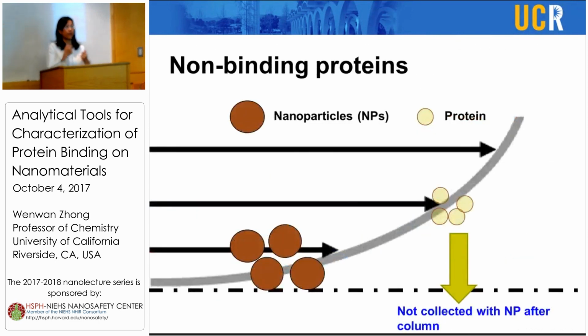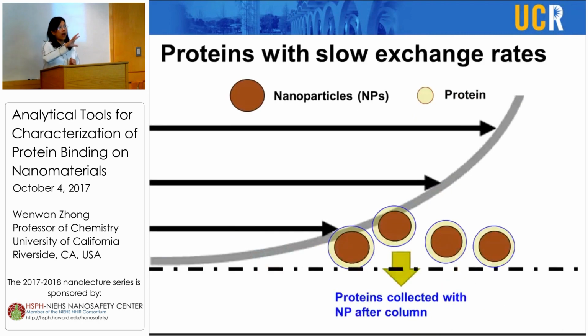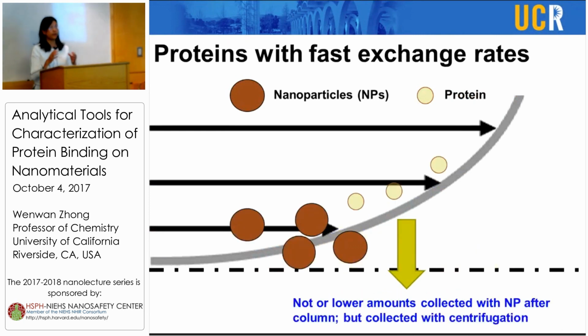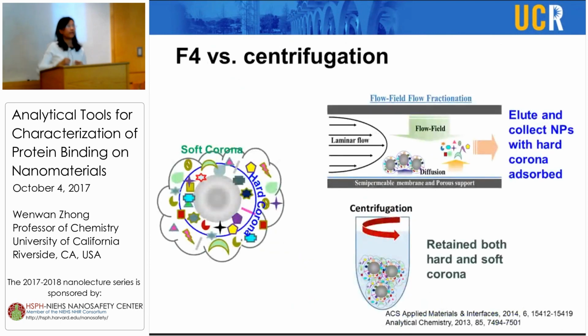So when we have a protein that is non-adsorbed onto the particle, because this particle size is quite different from a regular protein, with molecular weight around 100 to 150 kDa, the particles are much larger, right? So we can separate the particle very well from the non-adsorbed protein, and when we collect the particle, those non-adsorbed proteins will not be collected together. But we will have the hard corona coated outside of the particle when we collect it, because those proteins adsorb so stably that inside the column they did not completely dissociate, or most of them still remain bound onto the particle. And the soft corona would be the protein that is significantly depleted in the column, but we should still find them if we use centrifugation.